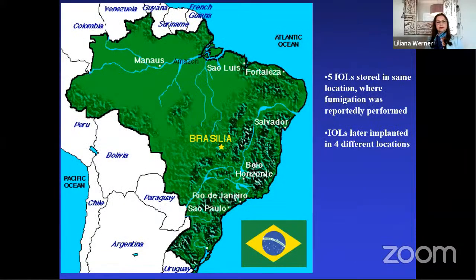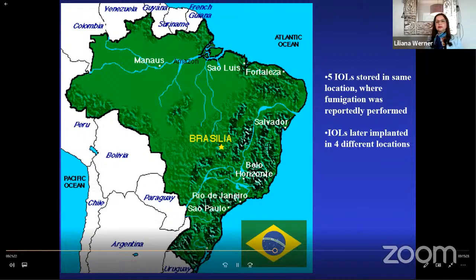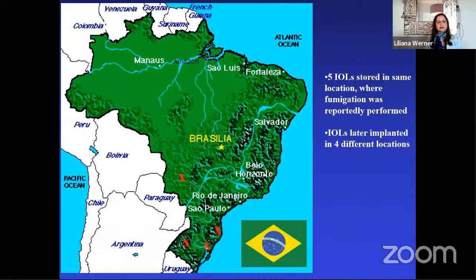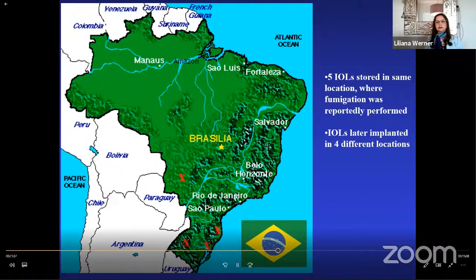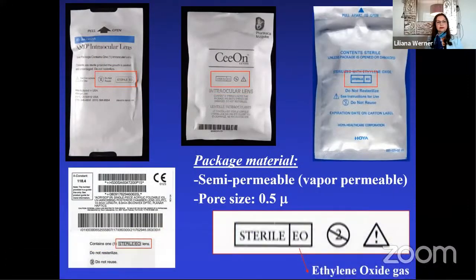Using the serial numbers and with the help of the manufacturer, we figured out that the lenses were stored in the same location in Brazil where fumigation was performed because of cockroaches. After storage in the same location, the lenses were sent to 4 different locations in Brazil, and all of them later presented the same type of early postoperative opacification. We cannot forget that these lenses are sterilized by ethylene oxide gas, and they are placed in semi-permeable packages for that, so other molecules in vapor may penetrate the packages.